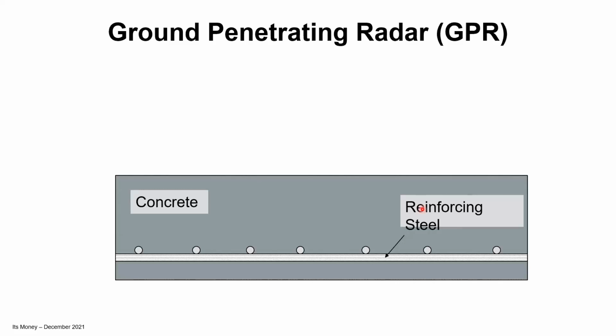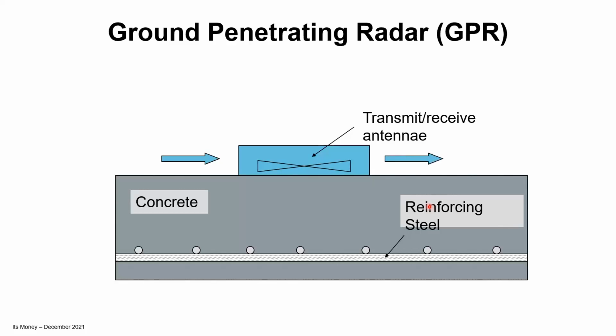Problem with radar is that it's measuring the dielectric constant of the material, and any significant change in that dielectric constant generates a reflection. Steel embedded in concrete provides a very strong reflection, which, if you have grade beams or caps in place, can help you identify where a foundation is, but you won't get much information through the foundation because you're going to get reflections back from the steel. The antenna transmits a microwave impulse basically down through the concrete. It gets reflected back from changes in the dielectric constant, in this case the reinforcing steel.